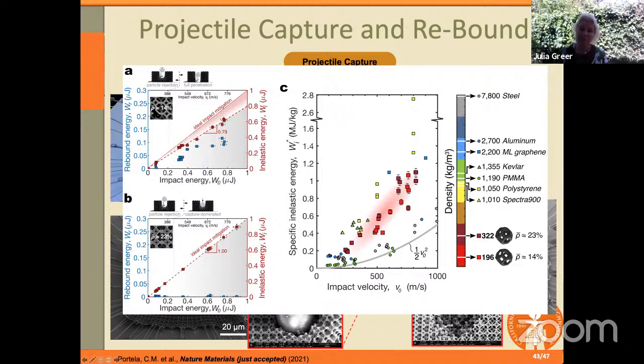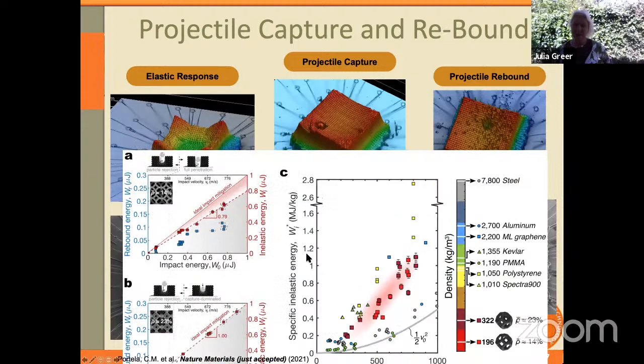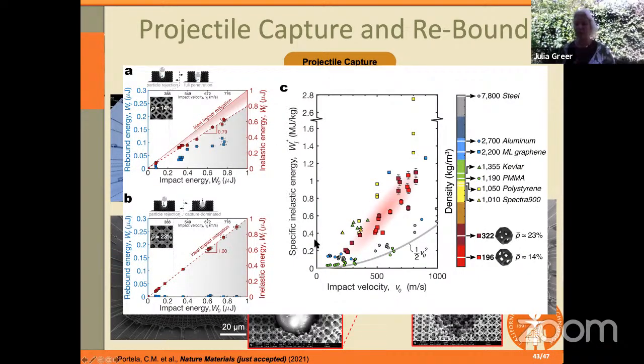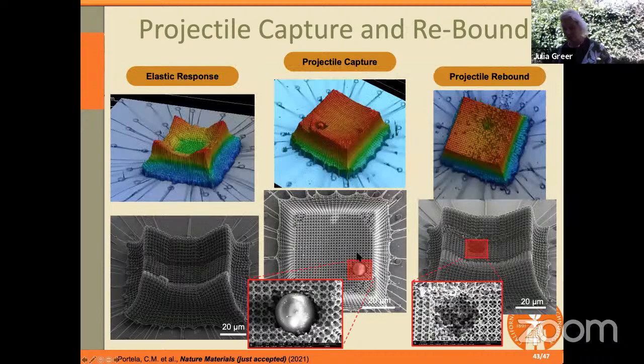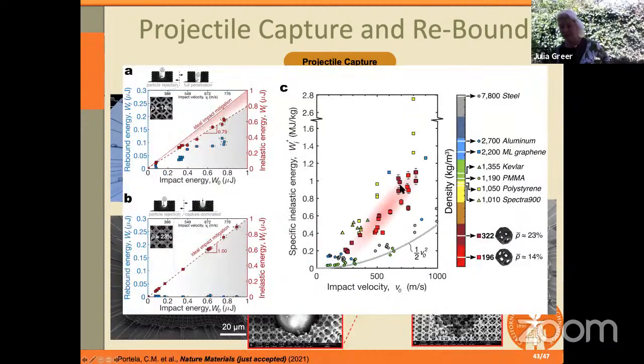Now, this is for the relative density of 14%, so these are very, very porous. As soon as we increase the density to about 23%, so it's about 1/5, they're still not very dense. You can see that we get very close to the ideal impact mitigation, in the sense that all the impacts are absorbed. And when we plot the specific impact energy, normalized by density or by weight, you can see that our materials actually outperform Kevlar and many other materials that exist today, especially at impact velocities that approach 1 kilometer per second. So we're very encouraged by these results and are hoping that there will be some impact resistance and shielding that they offer.